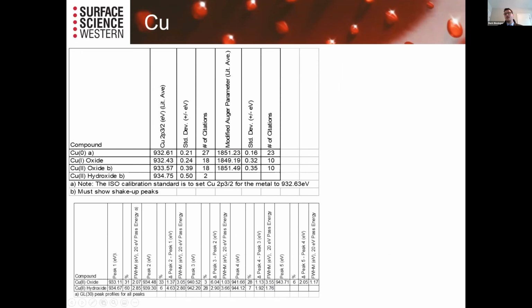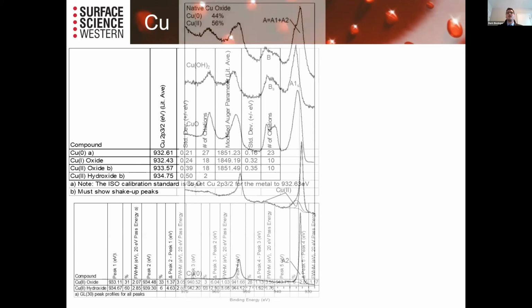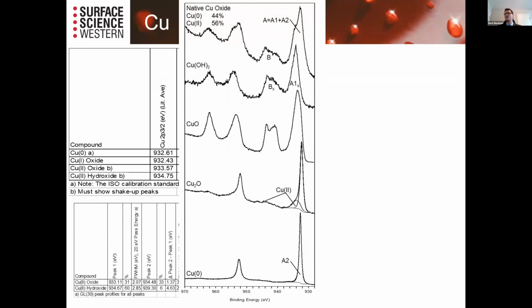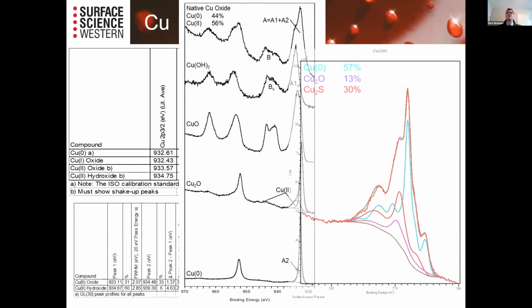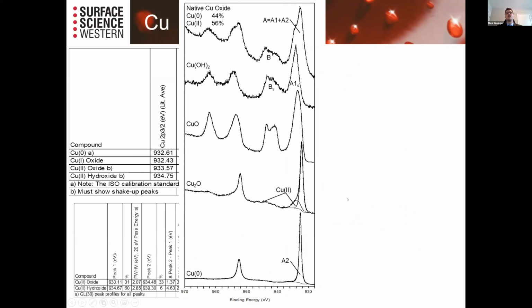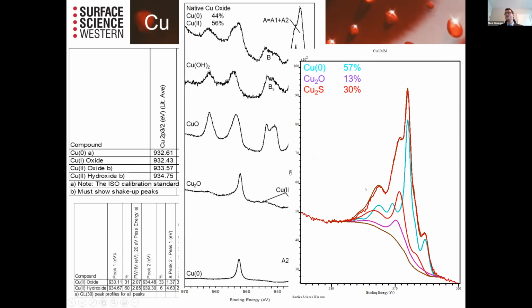We can do curve fitting of the 2p spectra. We can take a look at how much of a shakeup structure we have versus the main peak structure and do some math there where we figure out, okay, I have so much copper 2 versus copper 1 or copper 0 species. And then we can do curve fitting of the Auger spectra and again derive what materials we have. And this is particularly useful for copper 1 species. If we go back here, copper 1 species and copper metal have basically this one sharp peak that overlaps, and there's very little shift for any copper 0 or copper 1 species, but there's a lot of change in the structure of copper 1 species in the Auger structure or Auger peak. And so we can figure out, for example, how much copper 1 sulfide versus copper 1 oxide we have. And so that's our latest work that we've been doing.